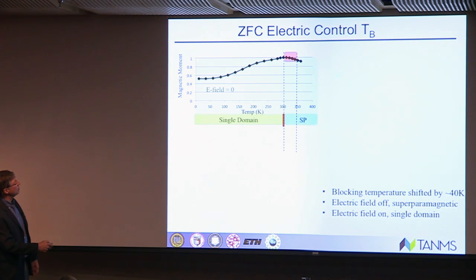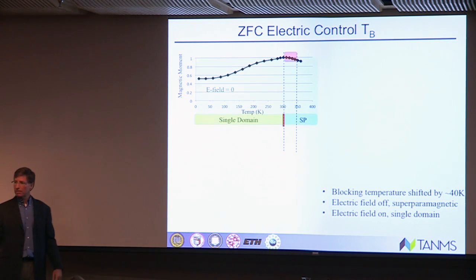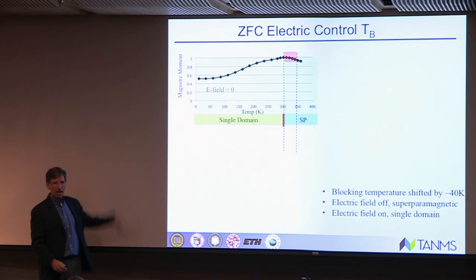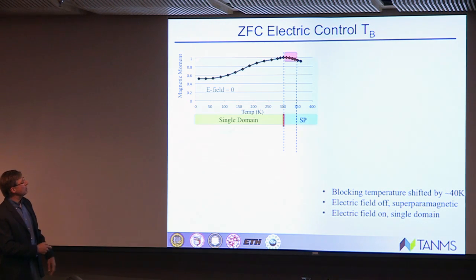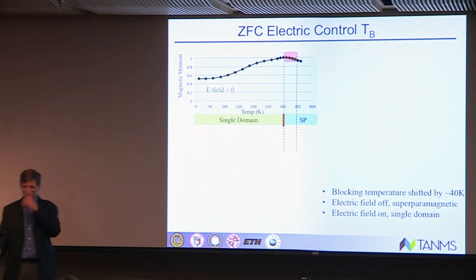You take the system, you cool it down to cryogenic, right around 0 degrees Kelvin. Then you apply a very small magnetic field, and you watch how the magnetization state changes as you increase temperature. And you'll get to a point where it maximizes, so the spins are aligned, and then above that point, it's superparamagnetic. We call that the blocking temperature. This measurement was done on the as-fabricated particles on the PMN-PT substrate.